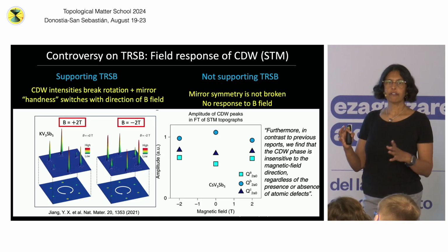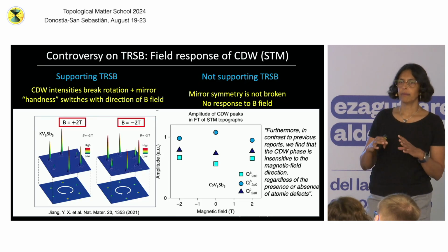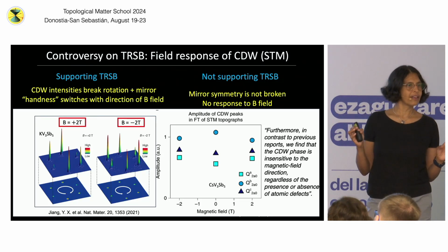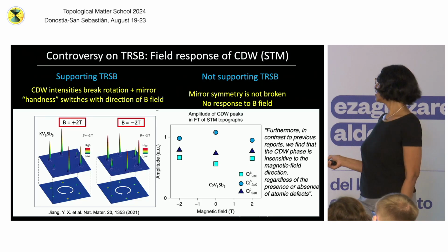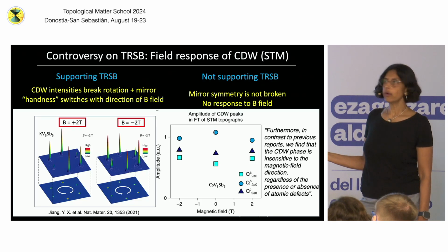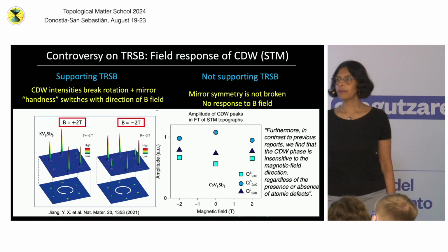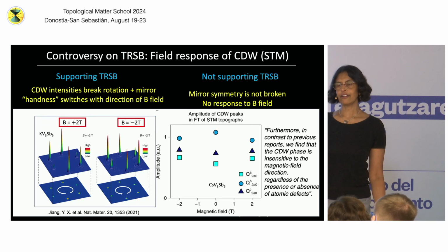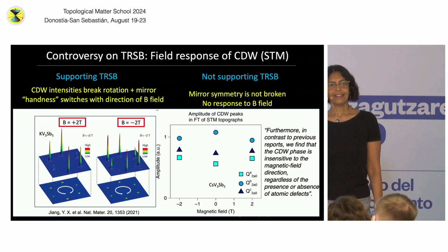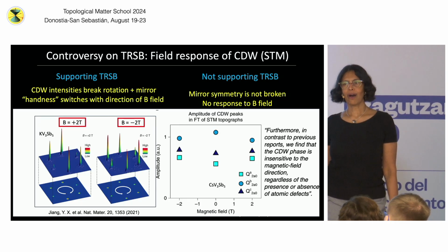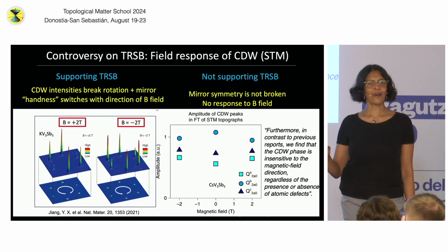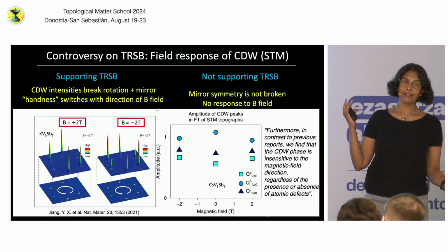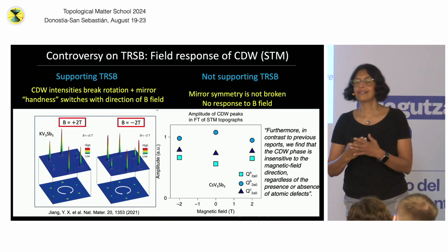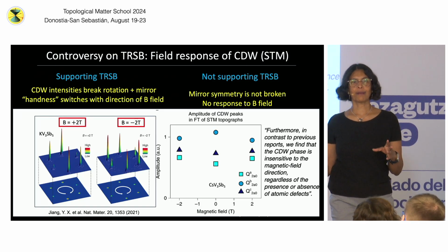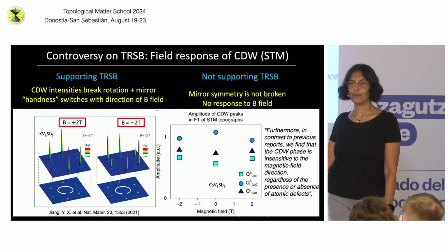Immediately afterwards, there was a lot of controversy. Different groups started showing different things. The first thing is the original STM experiment by Jiang was not reproduced. There was another group that did measurements and didn't see this kind of magnetic field sensitivity, right? The controversies are irritating, but they also are extremely interesting. Whenever there's a controversy, there's usually a reason for all these controversies, and sometimes you're able to figure out what's going on and sometimes not. I believe here I can tell you what's going on.